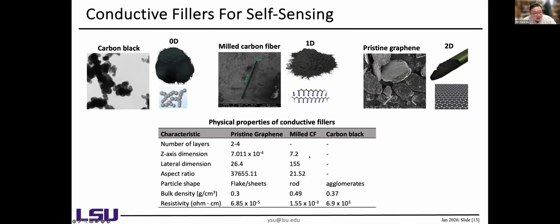As I said, for 0D, 1D, and 2D, we start from carbon-based materials. Carbon black is a 0D material, it's a powder form, and milled carbon fiber is a 1D material, and for the 2D material, we got pristine graphene. We collaborated with different companies to source these materials. And this table just shows you the properties of the different conductive fillers, including the shape, the density, and the resistivity. The difference is large.